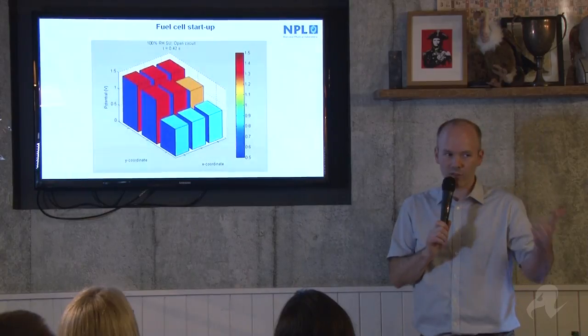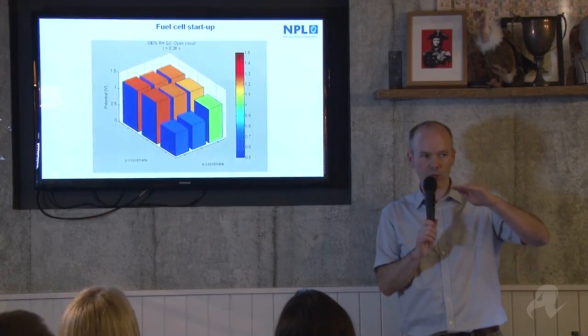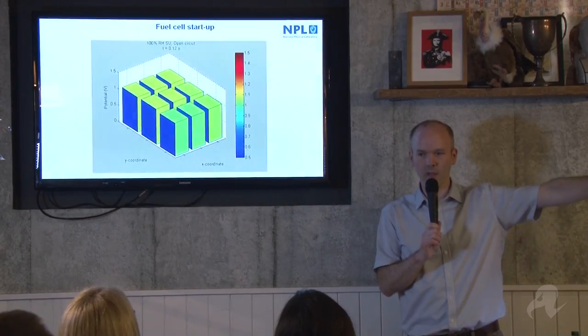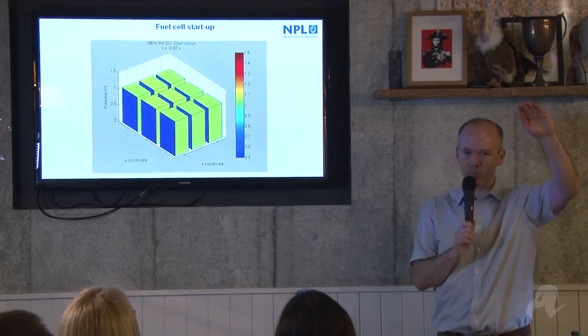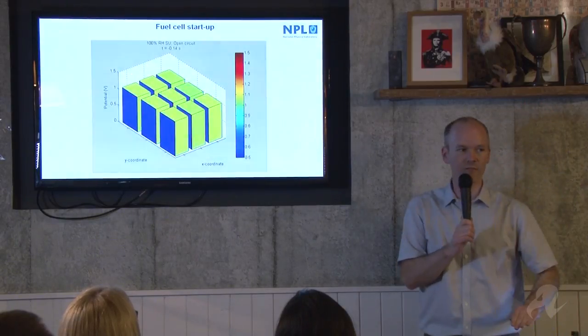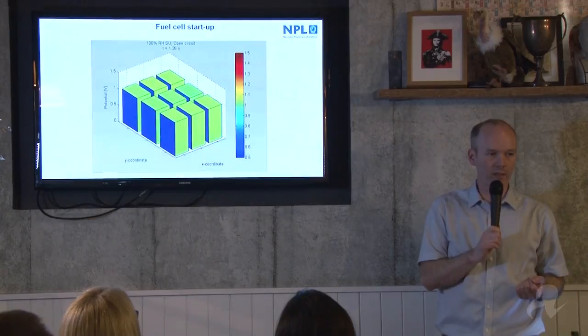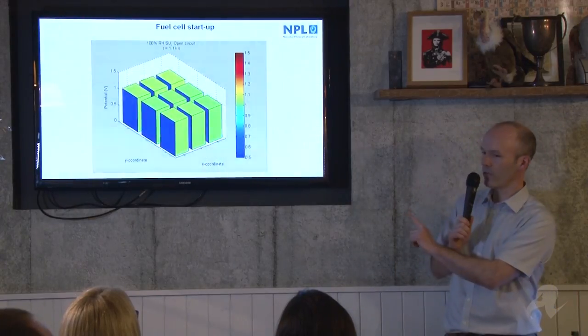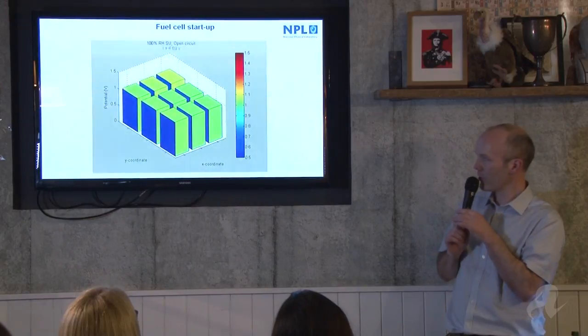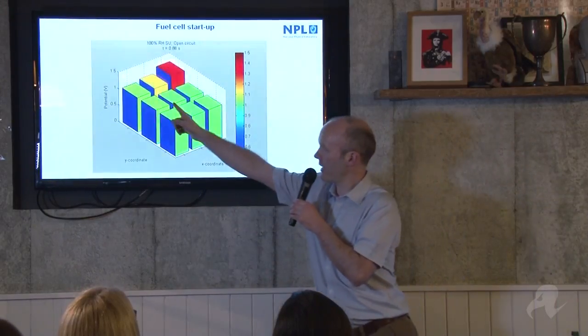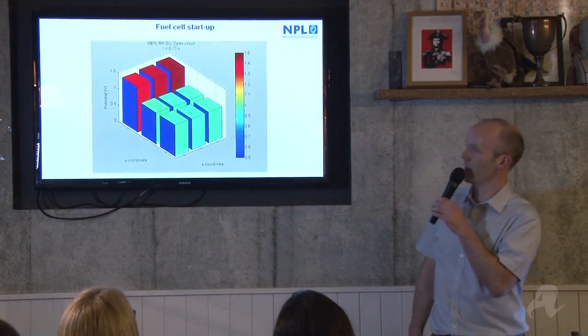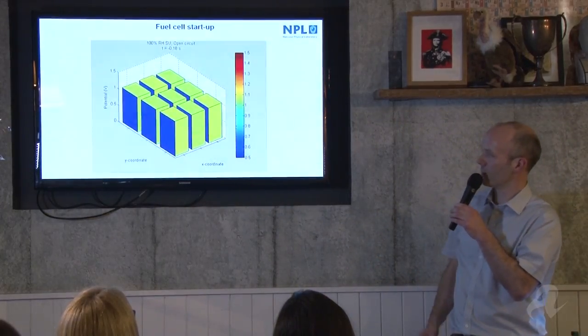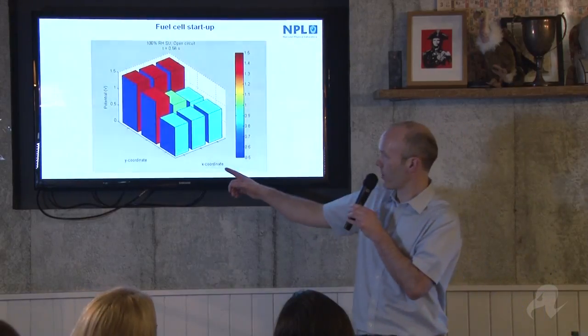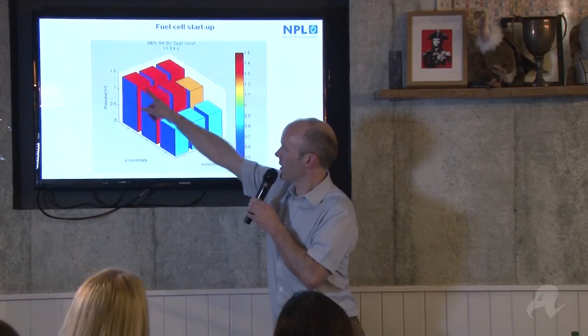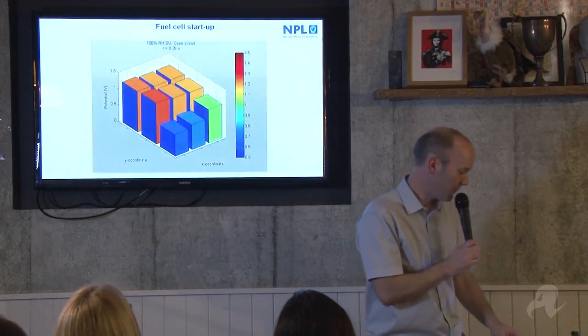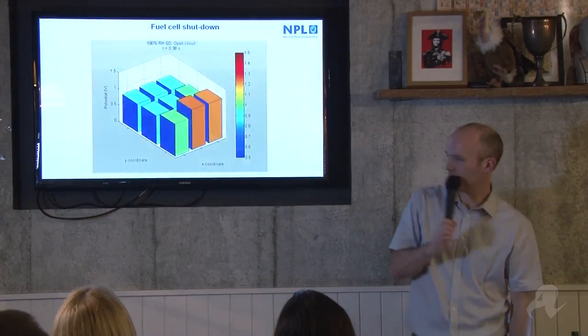And like batteries, like fuel cells, like electrolyzers, if you want to just run them at a constant current, they will last forever. What they don't like is the current going up, current going down, start, stop, on, off. The materials in these systems don't like that at all. That's what causes degradation. So we were very interested in startup and shutdown. And you can see from our potential measurements, we could locate inside the cell where the corrosion was happening during startup and for how long. So you'll notice during startup, this part of the cell is suffering the most corrosion. When we go to shutdown, we'll see the opposite happens.